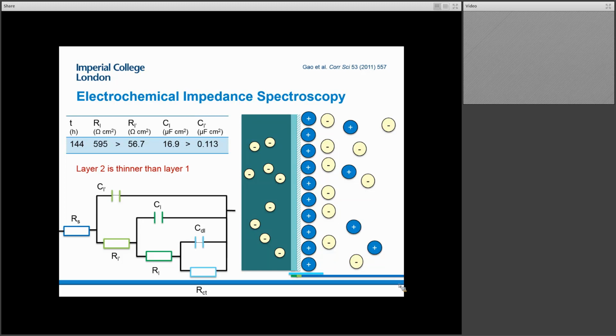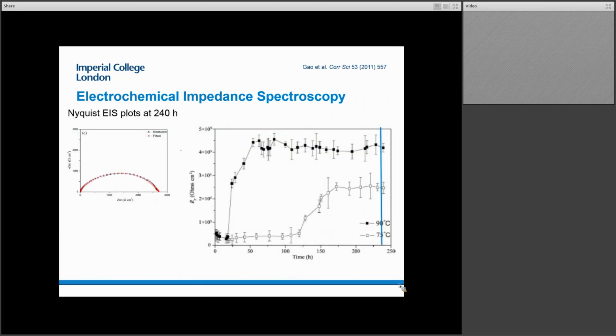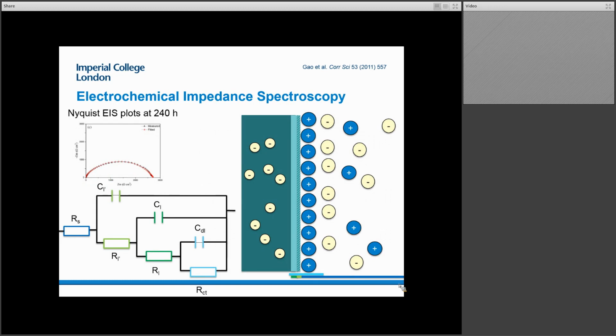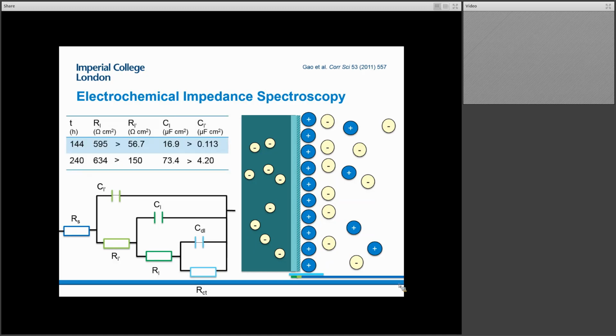And another thing is looking at that capacitance and how it's evolving. And so that's where it becomes interesting, because we know that in that intermediate time step, we were building what we think was some sort of additional resistance, i.e. through a second layer. So the question is, well, how does that change as we reach the final time point? So it would be reasonable to suppose you have the same structure. And so the question becomes then, well, how is that layer actually changing and what's interesting about it? And so they do see some evolution in terms of the resistance and capacitance in the layers individually and comparatively.